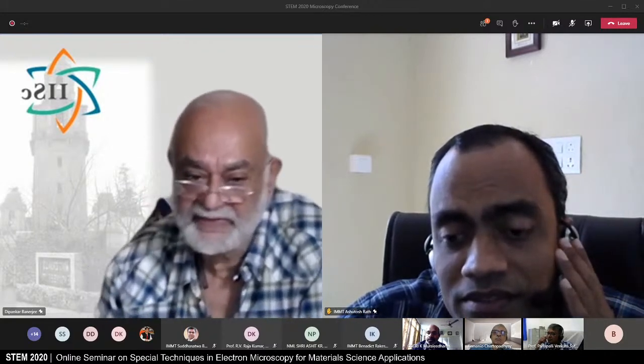Yeah. Ashutosh, that was a very important comment, and perhaps I didn't emphasize this at all in my talk. But interfaces control materials science and engineering in nanometric structures and in micron scale structures. Interfaces are extremely important. Whether it be grain boundaries or phase interfaces or whatever, the ability of the modern aberration corrected microscope to provide probe sizes of the order of the atomic size allows us, as you say, not only to define atomic structure and chemistry, but also to look at valence states across interfaces. Exactly. To look at phonon dispersion across interfaces. It's amazing what you can do today with electron energy loss spectroscopy.